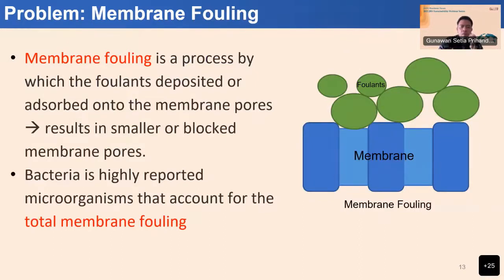So the problem with the membrane is that it is prone to fouling. I mean, when some foulants attach and deposit on the membrane pore or on the membrane surface, it may block and also create some growth on the membrane surface, and afterward finally it will make the membrane become impermeable. And bacteria is one of the microorganisms that cause the problem of membrane fouling here.